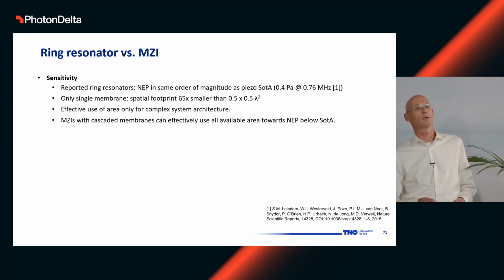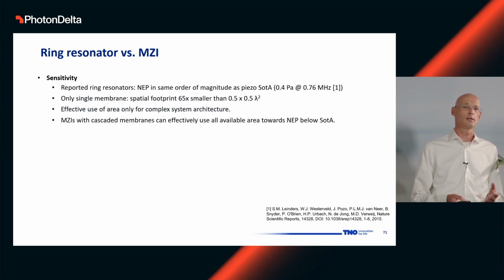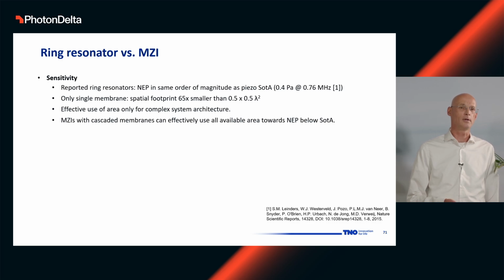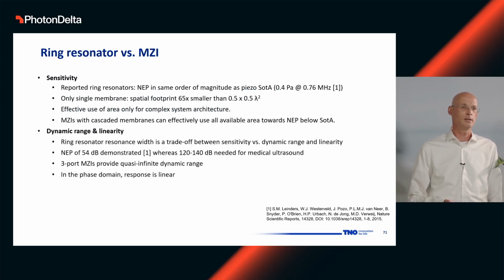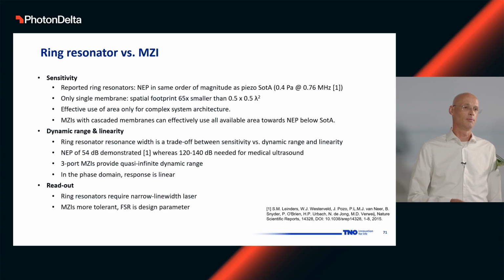So when it comes to comparing ring resonators and MZIs, I have to go a bit quickly through this. When it comes to sensitivity, with ring resonators, sensitivity is in the same order of magnitude as what you have in typical piezo transducers. However, they use only a very small area. And the key thing is that you have to make effective use of all this area within an acoustic wavelength. This can only be done in a realistic system by means of these Mach-Zehnder interferometers with cascaded membranes. And when it comes to dynamic range, ring resonators are very limited here, whereas in MZIs, the dynamic range is virtually infinite. And when it comes to readout, with ring resonators, you need a pretty expensive narrow line width laser to account for phase noise issues, whereas MZIs are way more tolerant than that.